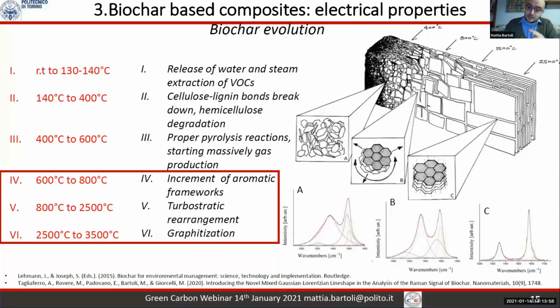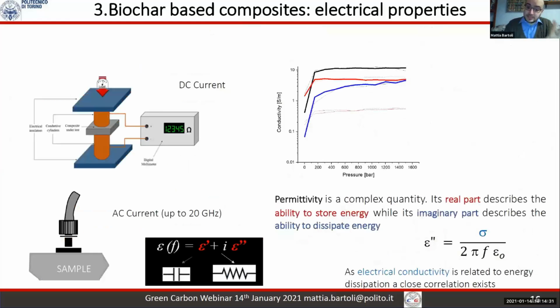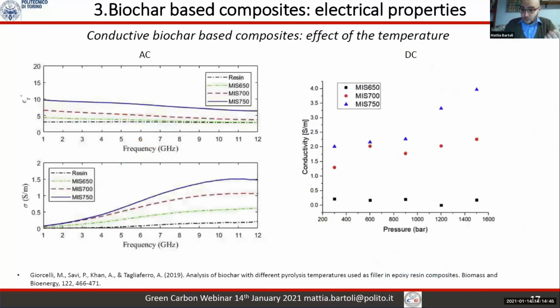On the right of the screen, you can see the evolution of biochar monitored by Raman spectroscopy. Here there is a particular way of approaching Raman of disordered materials that we developed for the analysis of biochar. But you can see that at higher temperature, biochar becomes more graphitic, even if it is a non-graphitizable carbon type material. As in the case of mechanical properties, we compared biochar with CNTs by using mainly two different approaches, one in DC current and one in AC current, to evaluate everything that we can check. Before this, we confirmed that temperature is relevant for conductivity. Even an increase of 100 degrees during the production of biochar induces a very different conductivity in the final material, as you can see here for miscanthus.